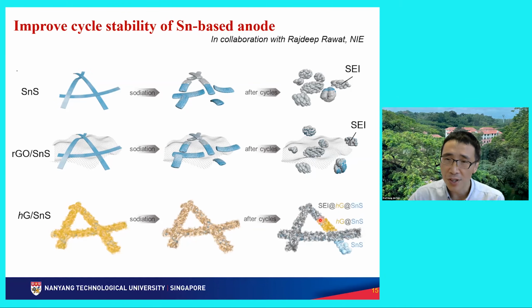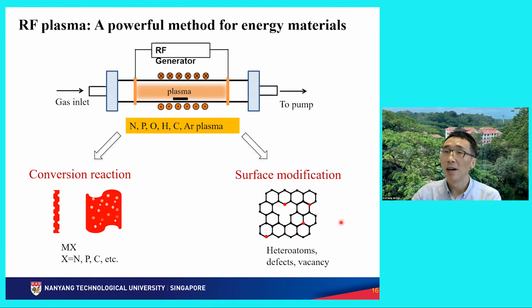So with this structure design, the whole thing is conductive carbon, and it's wrapped around the whole surface there. After many cycles, the tin monosulfide breaks into polycrystalline particles, but the particles are still surrounded, encapsulated, or encompassed by the graphene surface coatings. And they will not form the SEI layer directly on the active material. Instead, they form on the outside surface of the graphene. We call it hierarchical graphene. So this simple design actually has a lot of good outcomes.